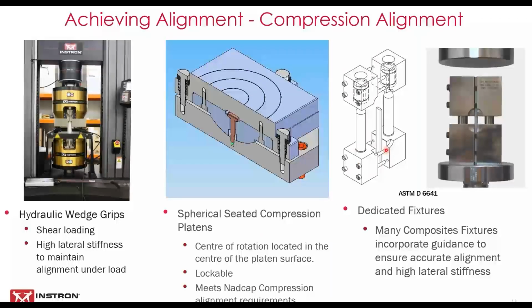Then there's a whole raft of composite fixtures, particularly for compression, which actually integrate guidance and alignment into the fixture. So one example would be the ASTM D6641 combined loading compression jig, which you see a picture of here and a diagram showing the bearings, and obviously this is laterally stiff and well guided. So this would simply be used between sets of compression platens on a machine, but the guidance is actually coming from the fixture rather than the machine in this case.